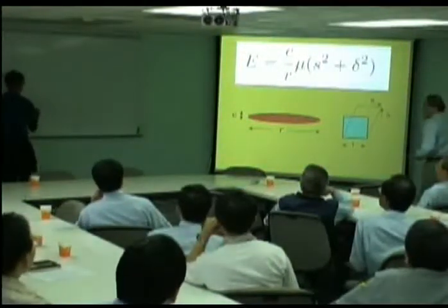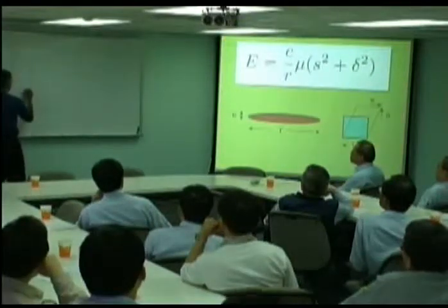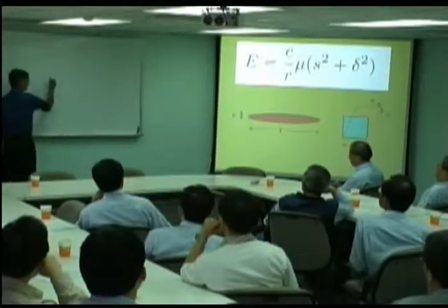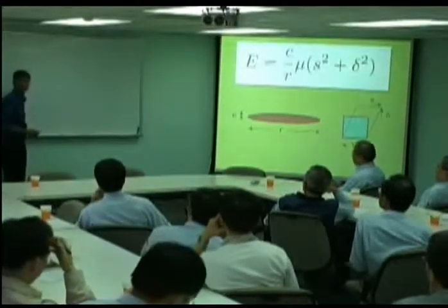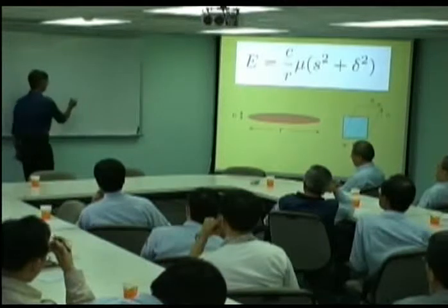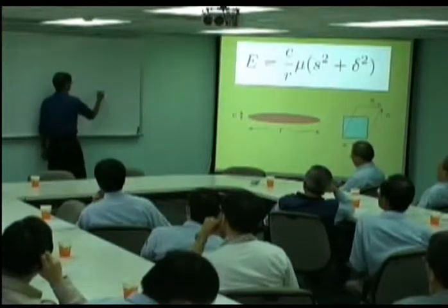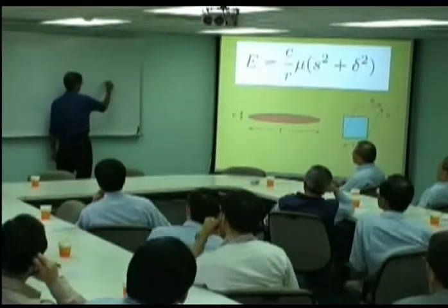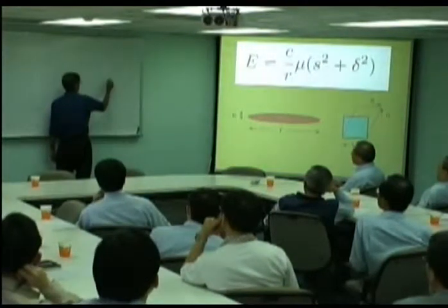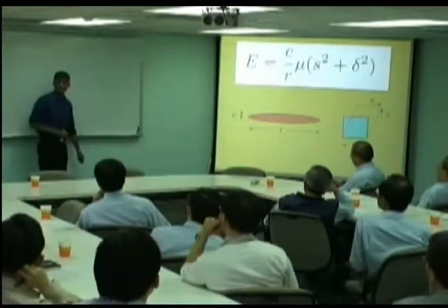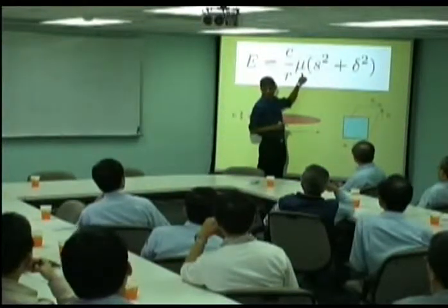Now, the origin of this equation is very simple to explain. First of all, if I plot stress versus strain, the elastic part, then the area under this curve is simply the strain energy per unit volume. So the area under that curve is half stress times strain, which is equivalent to half the modulus times strain, so epsilon squared times the modulus. So you can see we have the strain squared times the modulus.